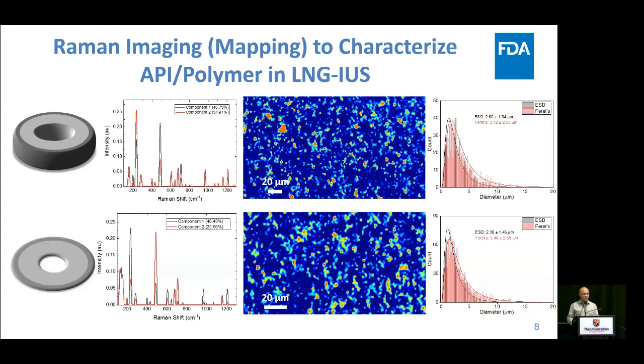But essentially, you're really collecting data from a cone. And considering that PDMS is translucent, it is not a very good Raman scatterer, whereas the LNG is. So we do have a lot of out of focus contribution that's coming from beneath the surface. So our analysis here is not only biased for larger size particles, but it's also perhaps not representative of the true surface, right?